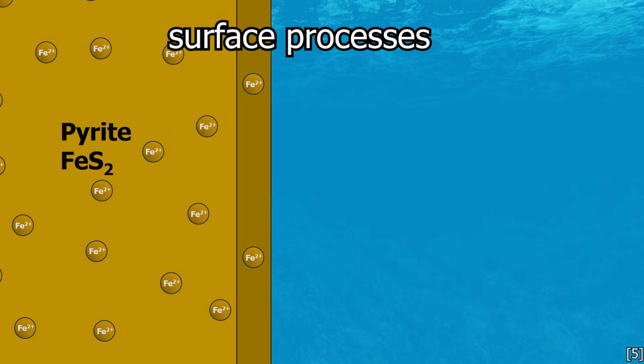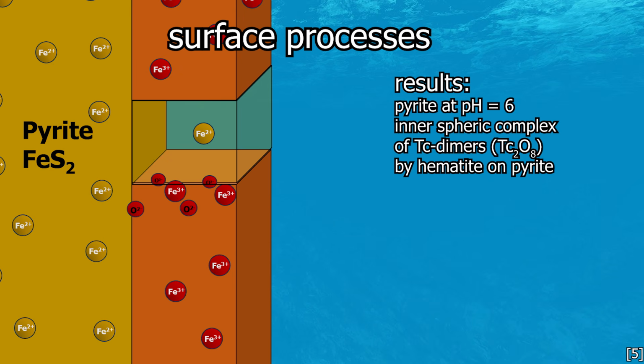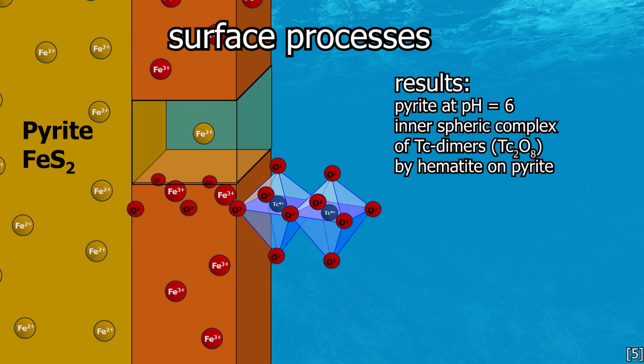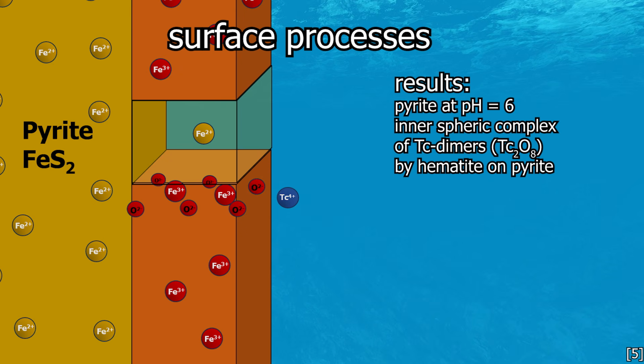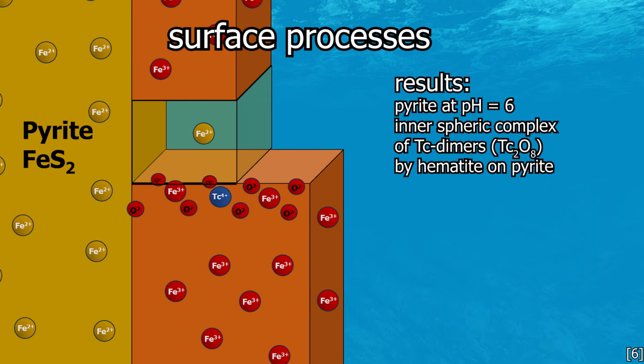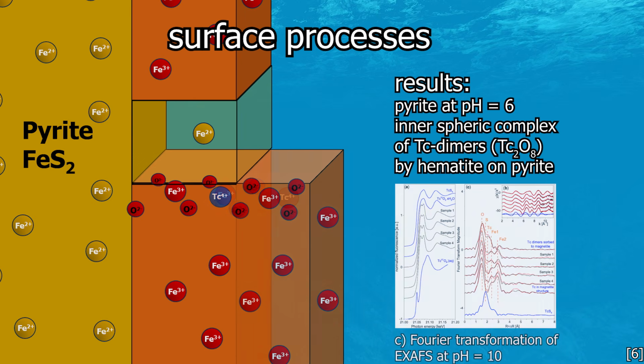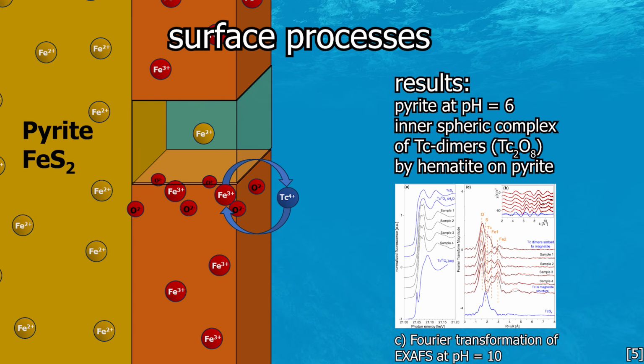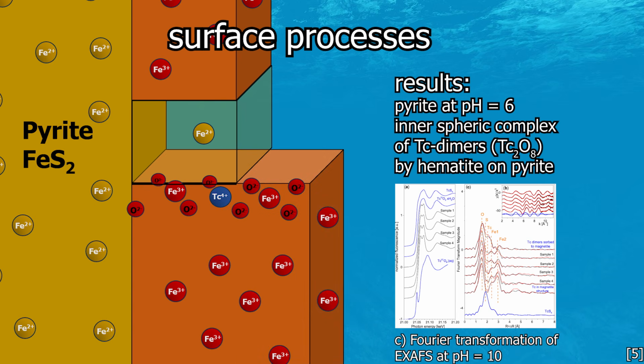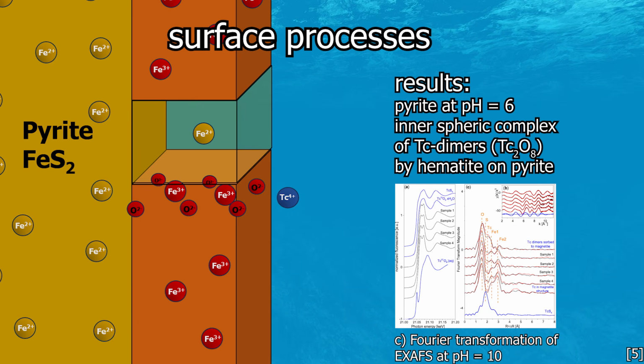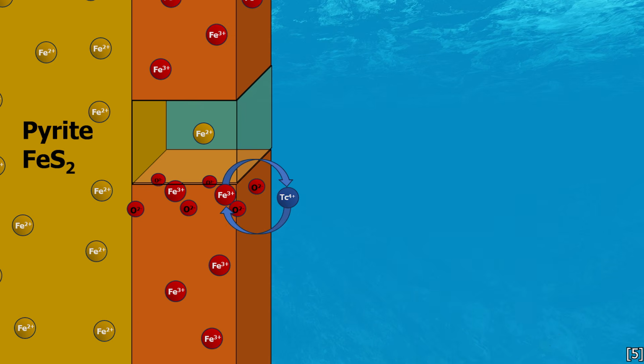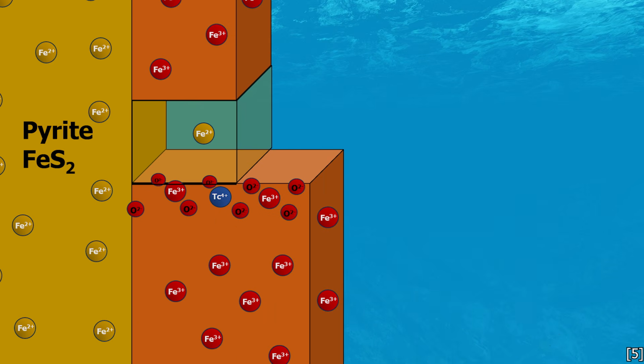And then there is the strongest type of immobilization, namely incorporation into the mineral. Technetium 4+ can replace iron 3+ in the crystal lattice as both have the identical crystal radius. This means that during the redox process, the iron ions can actually dissolve out of the crystal. Technetium can be incorporated into the structure of the existing iron oxide, and then the mineral can continue to grow as magnetite behind it. This iron oxide layer is passivated. The technetium is practically buried in the mineral.